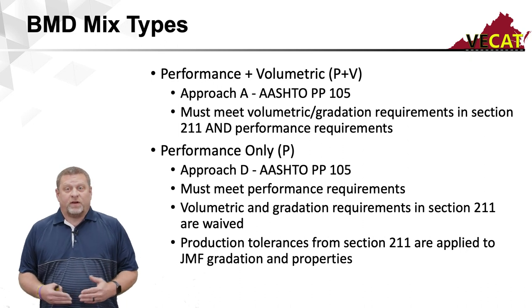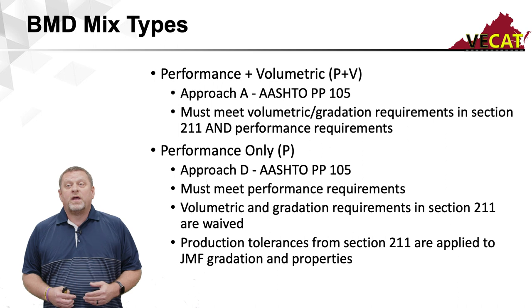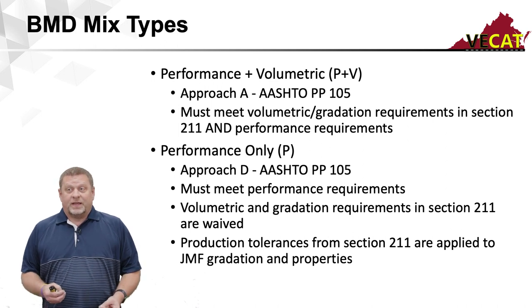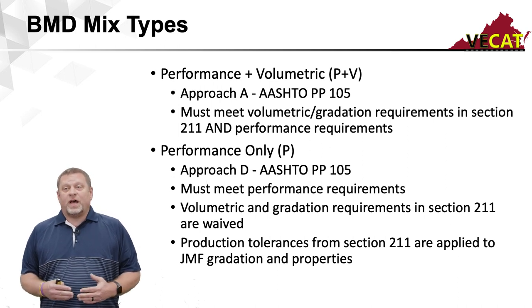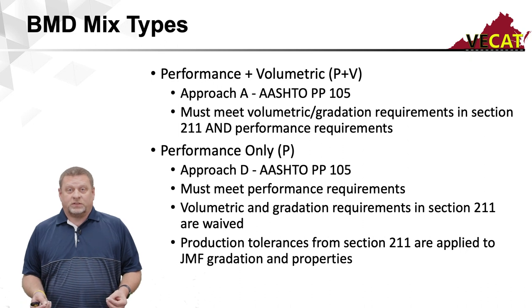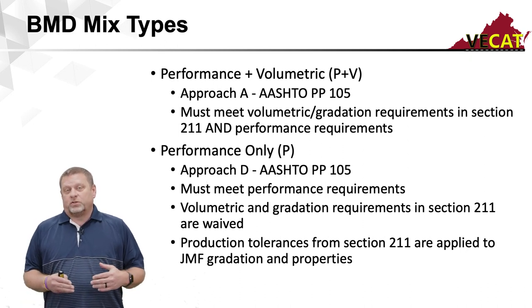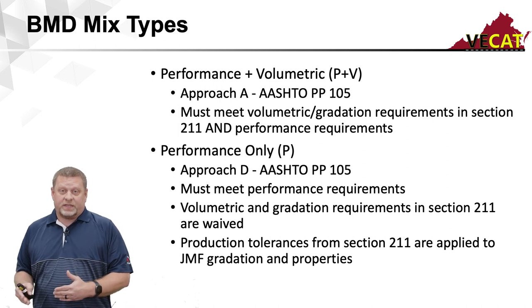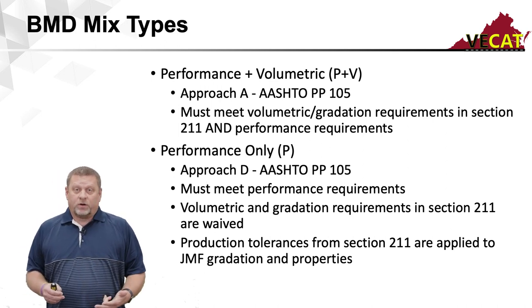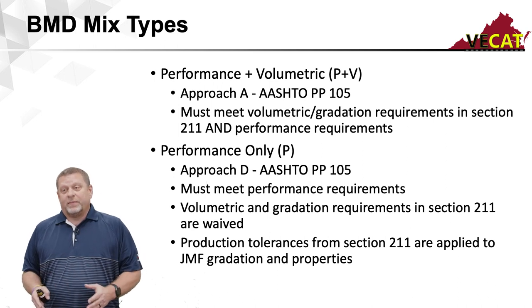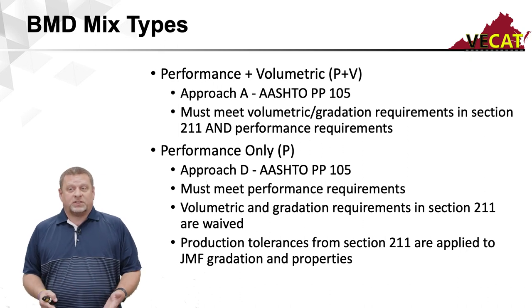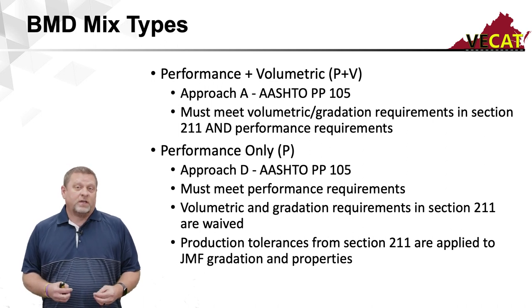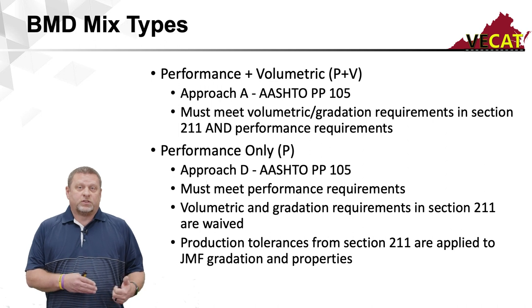VDOT also has, but you have to look at your contract to see which mix is being called for, a performance only mix. This one's a little different. During the design phase, you're not limited by any volumetric or gradation restrictions. You basically design the mix to do the best it can on performance tests or BMD tests: rutting, cracking, and durability. And once you get that mix design established based on performance tests, you then can go into production. Once we go into production, you will have to maintain production tolerances that are in Section 211, but you aren't limited to those tolerances during the design phase.